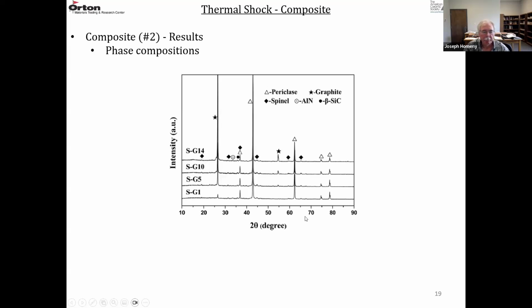This is just an X-ray diffraction diagram for SG1, G5, G10, and G14, and it's basically periclase and graphite. So the major peaks here, the triangles and the stars, are periclase and graphite. And then at the highest temperatures, because we have some aluminum and silicon metal in these materials, you get a little bit of spinel forming, a little bit of aluminum nitride. It's coked under nitrogen, so there's some possibility of forming aluminum nitride, and from the silicon metal and the carbon, silicon carbide. So there are trace amounts, the diamonds, the circle with the dot, and then the solid circle. You can see the peaks are just barely there. There are trace amounts of these other components.